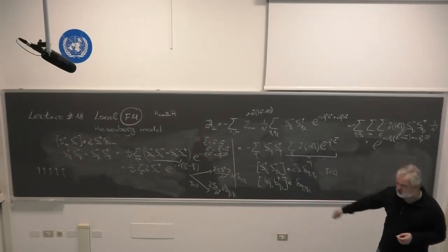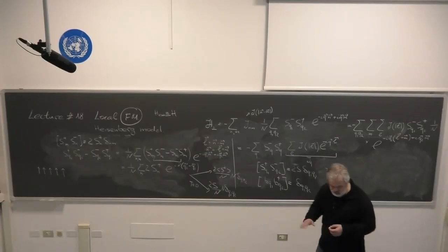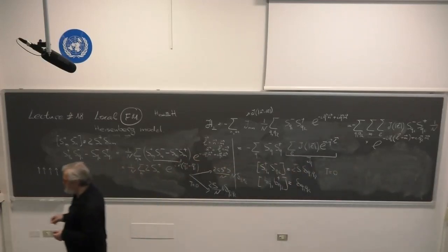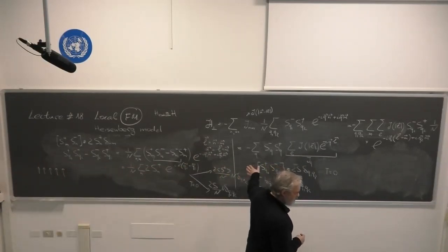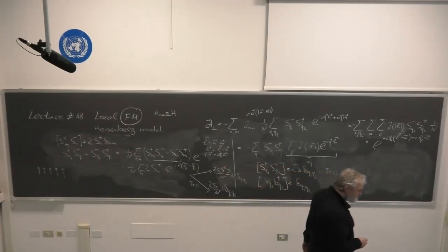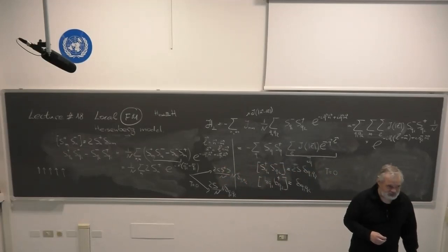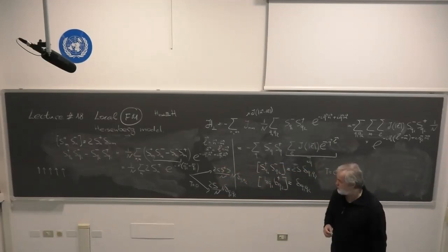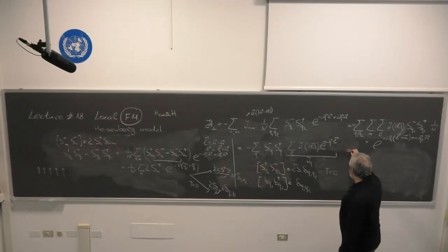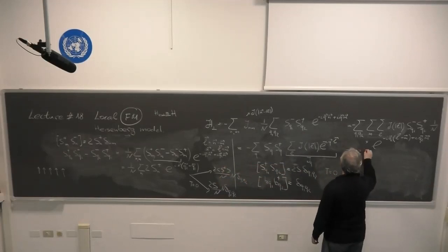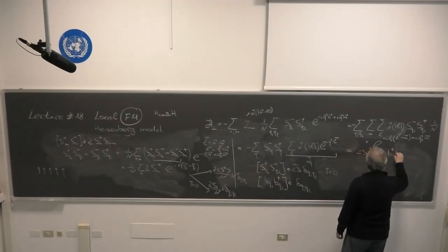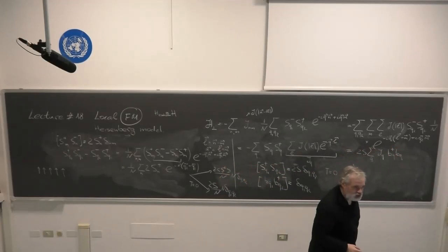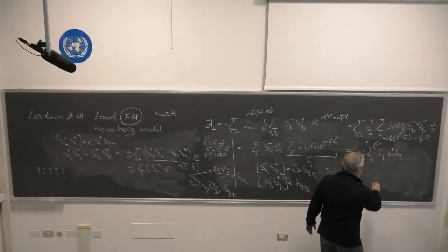Here, without losing any generality, I'm talking about a three-dimensional system, and I will come to a discussion of dimensionality a bit later. So it's just spin algebra, nothing else. And this is Holstein-Primakoff, by the way. This is a trick introduced in 1940. Good. So what I'm saying is that I rewrite this part as 2S sum over q, g_q b†_q b_q. So the transverse part is already written as a quadratic form in the right way of a harmonic oscillator.